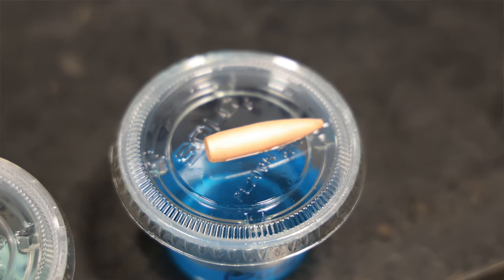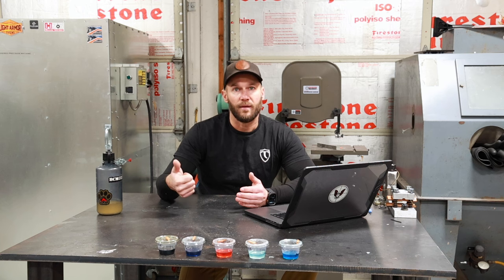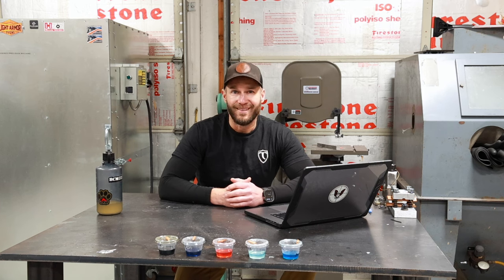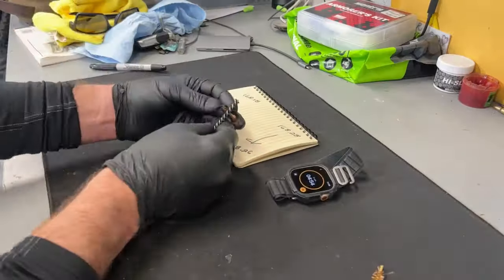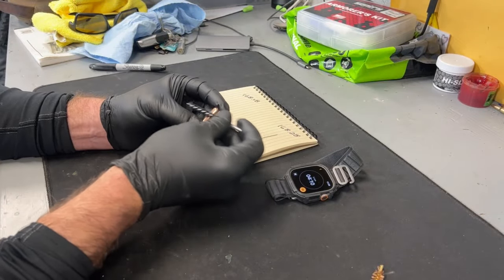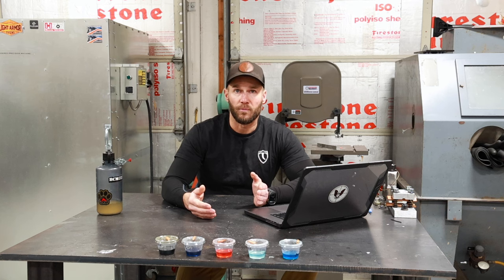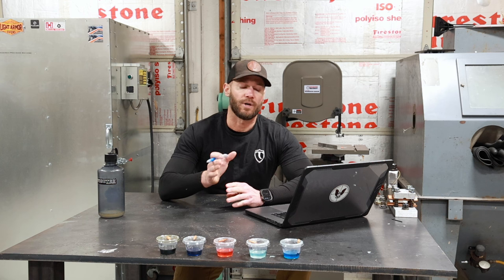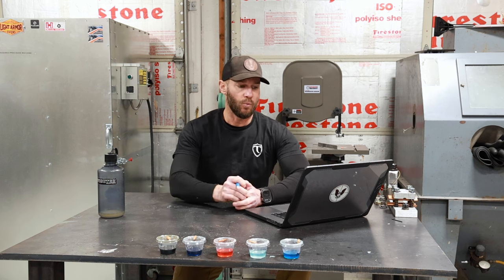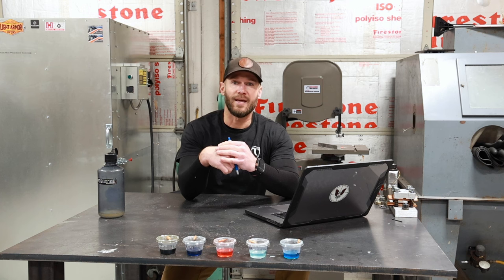After the chemical portion, I thought about mechanical methods of material removal: copper/bronze brushes and nylon brushes. I took another bullet, weighed it, and attacked it with a nylon brush for five straight minutes; did the same with a copper brush and another bullet. Then I weighed them afterwards to see if there was any mechanical material removal. Nylon brush: starting weight 168.18 grains, finished weight 168.18 grains — net change of zero.